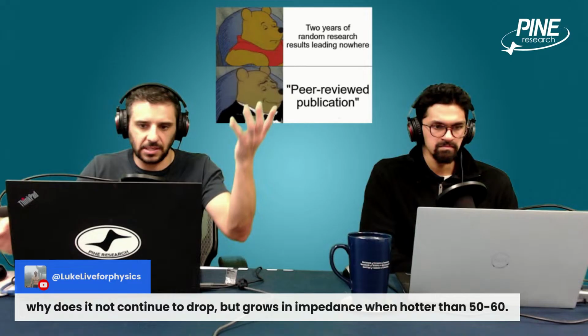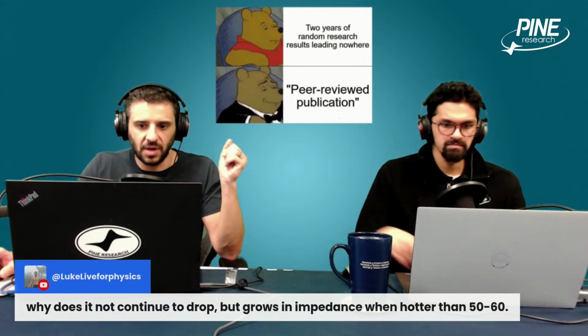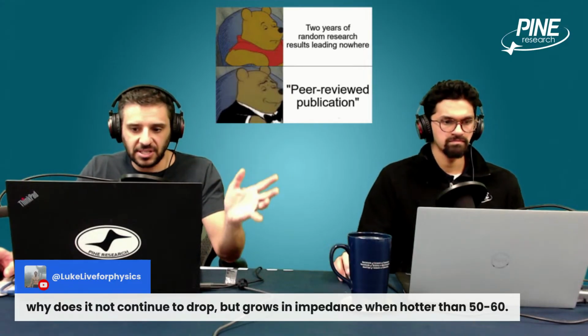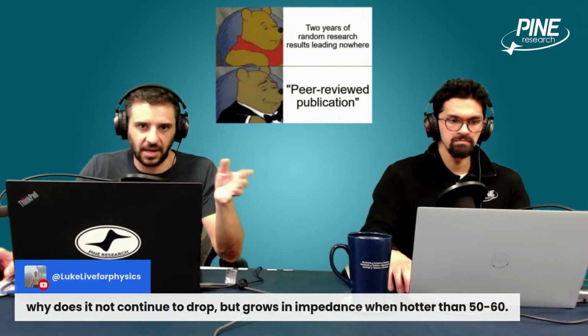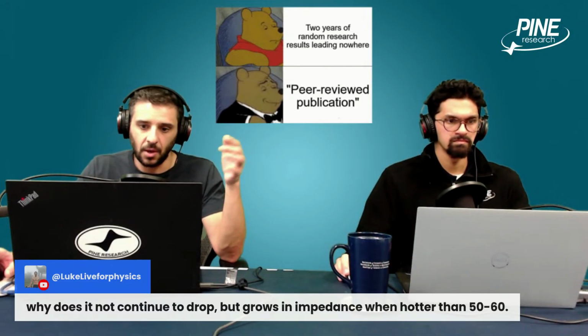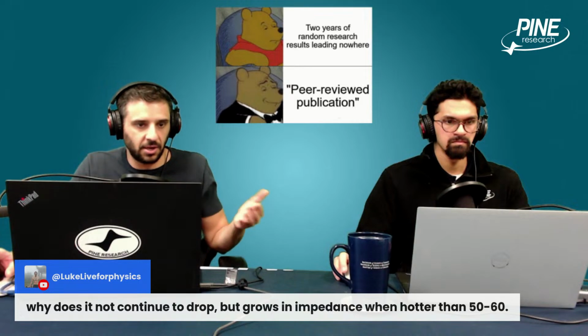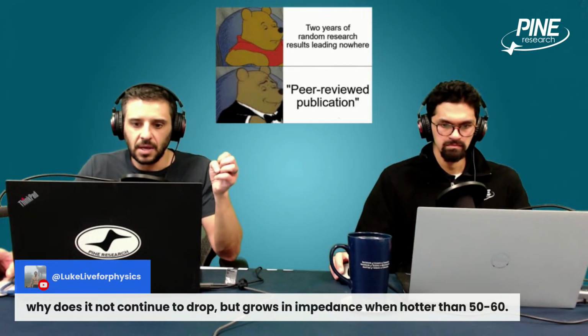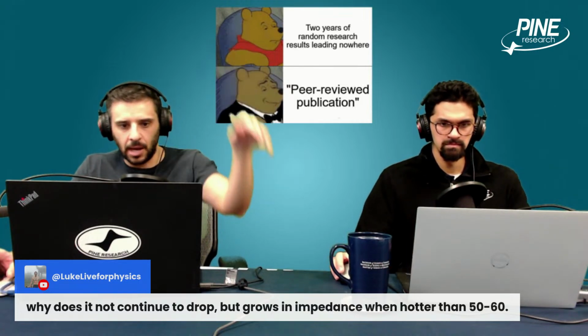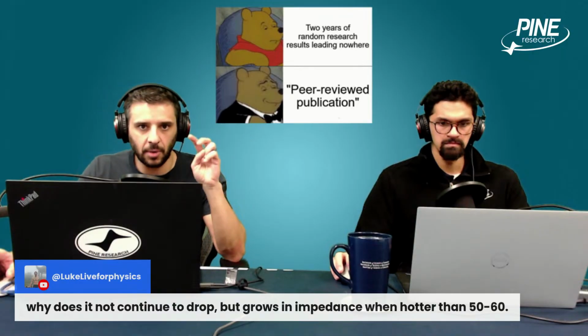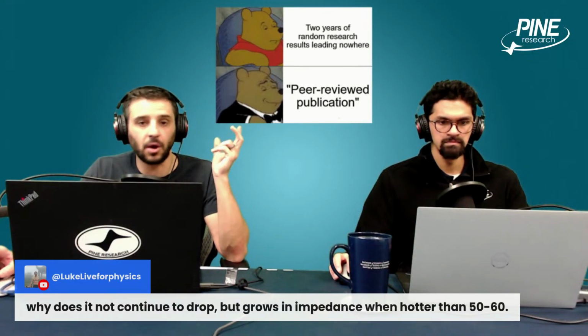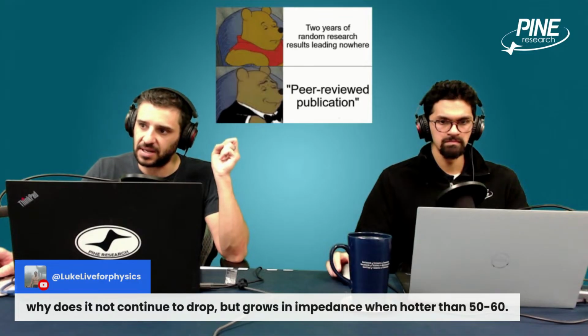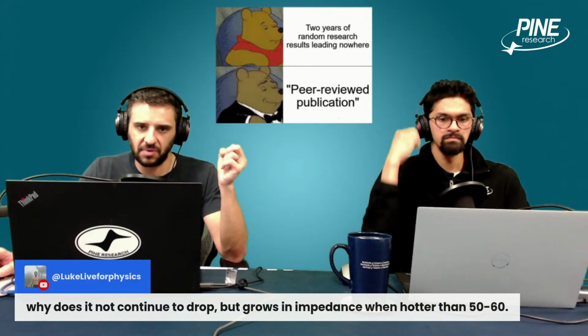Like, I'm just making this up. I have no idea if this is the case. Let's just say you do the anode test, and at every temperature and state of charge, its impedance is not predictably changing. Okay, well, then it's not the anode that's causing it, you could conclude. But you do the cathode and you see up then down or down then up behavior based on temperature. And then you might say, okay, it appears the cause of the dramatic impedance change is related to the cathode.